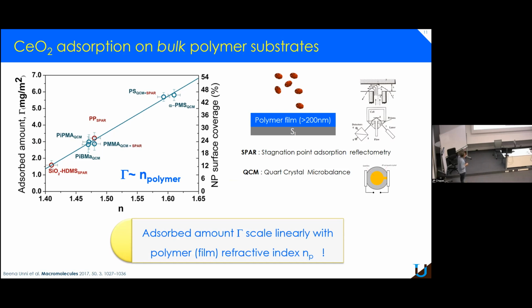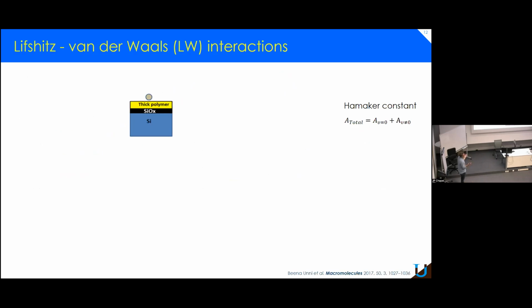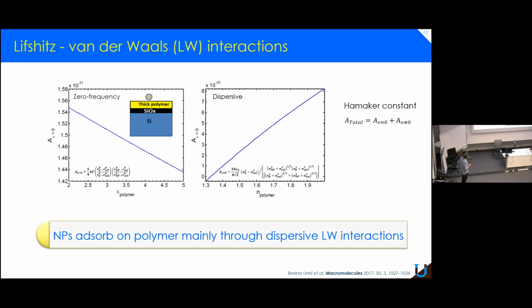So this is telling us that if we change the refractive index of the polymer surface, we should see a variation in the adsorption of the nanoparticles. If you do a little bit of simple calculation, you can convince yourself that the dispersive forces between the particle and the substrate are basically the main component of the adsorption. So nanoparticles, at least cerium oxide, adsorb mainly through dispersive Lifshitz-van der Waals interactions.